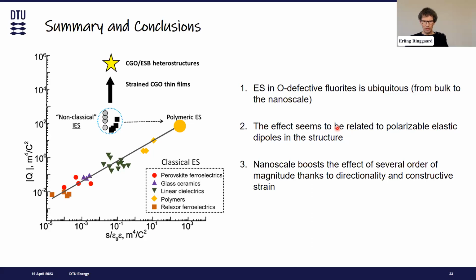The first one is, can you use the electrostrictive material for energy harvesting? The answer is no, because electrostrictors are basically only actuating. If you want to talk in terms of piezoelectricity, what we get here is the converse or inverse piezoelectric effect. It means that if you apply an electric field, you change the shape of the material. To do energy harvesting, you need the other effect. You want to harvest mechanical energy from mechanical waves or from a movement. You need to stimulate and strain your material to get an electrical signal. So the answer is no, unfortunately. But on the other hand, we can do motors or other actuators and other kinds of applications.